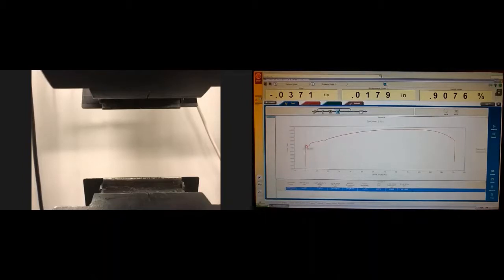So here we see Hooke's law in action, and we can measure the modulus of elasticity, measuring the slope of this linear portion of the curve. So here we don't have any dislocations generated, and the atomic bonds are just stretched to some limit. Maybe the limit is over here. It's called the elasticity limit, beyond which you can see some weird behavior, and this region is called yielding